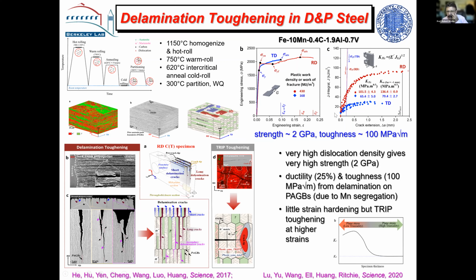And if you look at the toughness, provided you're in the same orientation, and this is the R curve here on the right-hand side, you can get a very, very high rising R curve. This is done in terms of the J integral, but if you convert it to K, this gives you a toughness of 100 megapascal root meters, which is pretty good for a 2 gigapascal strength steel. Now, how does that work? Well, once again, you look at the fracture surface and you see these delaminations perpendicular to the crack path, and they're much steeper delaminations in this case. And it turns out when you look at them, they occur along the prior austenite grain boundaries. And it turns out you get manganese segregation to those prior austenite grain boundaries, and that weakens those boundaries.